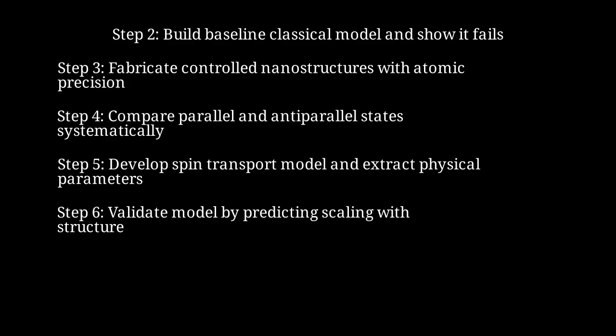Step 5. Develop a quantum mechanical spin transport model based on Mott's two-current picture and fit it to data to extract parameters like spin asymmetry. Step 6. Validate the model by predicting and confirming how GMR scales with layer thickness, number of layers, and interface quality.